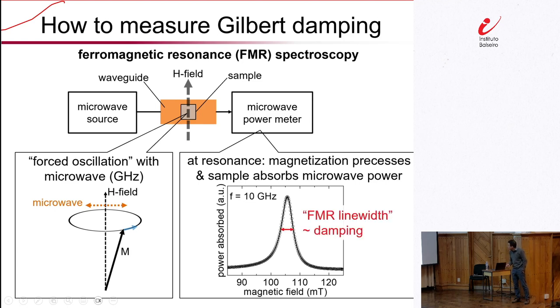So that's resonance. But we are here talking about damping, some kind of friction-like dissipation process. Just like any system that has resonance, a mechanical oscillator, an RLC circuit, and so forth, we can capture the amount of resistance or damping through the width of the resonance response. If you have a material with low damping, you expect to see a very sharp peak with a small line width. On the other hand, if you have a material with very high damping, you would expect to see a much broader, much more smeared out resonance response. So that's the basic idea, that the line width is related, at least in the simplest cases, to the amount of damping in the material.